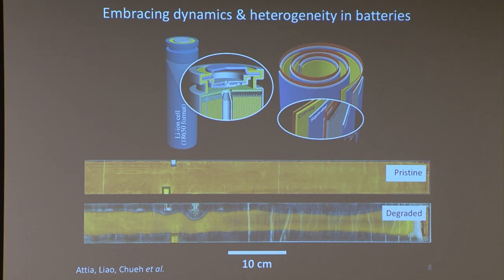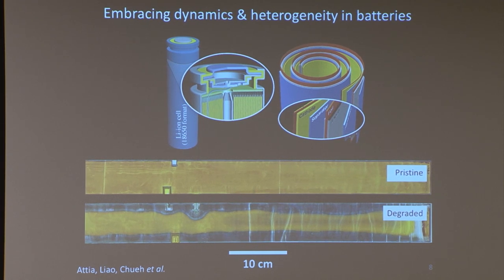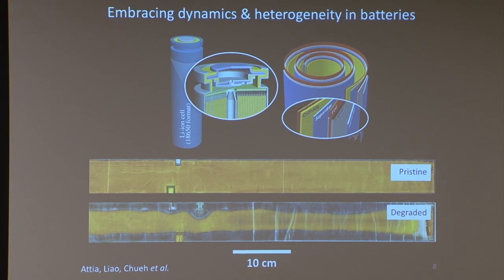The top row is when the battery is new. The bottom is after degradation over about a 7-month period. So you can see part of the battery becomes deactivated. And this is the centimeter scale. So take a look at the scale bar here. This is the device level characterization. So it's highly heterogeneous and also takes many months for the heterogeneity to develop.